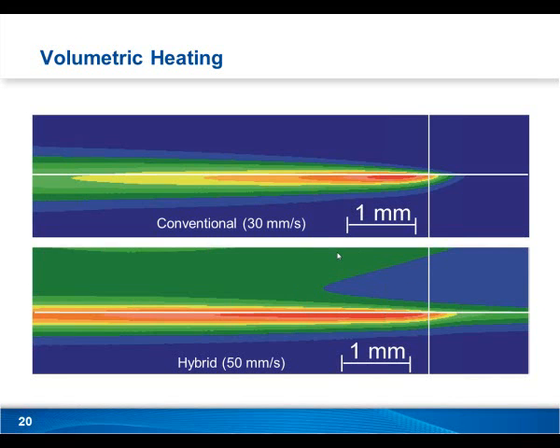This is important for a couple of reasons, and we'll definitely get into these as we go on and talk about the advantages of it, but by increasing this heat, we can do things like speed the laser up. We're going to reduce stress in the part compared to regular conventional welding or other welding methods. And as you can see here, hybrid is faster at 50 millimeters per second, 30 millimeters per second.